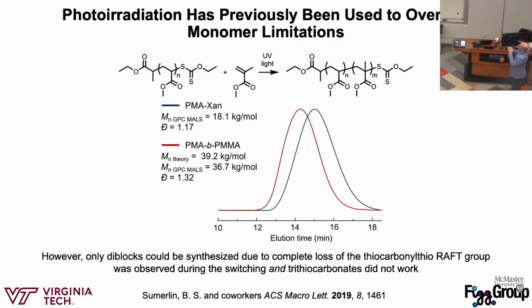But they were able to just homolytically cleave this through UV light, and then they can make this block copolymer of methyl acrylate and methyl methacrylate. They actually lose a lot of the chain end also, even though I have it drawn here, but you can chain extend it. The big issues with this is that you lose the chain end retention, and then this only works for xanthates. If you ever do RAFT polymerization, or you want to get interested in doing RAFT polymerization, xanthates are very rare in conventional RAFT polymerizations that you do because they don't lead to as good of control due to some of the energetics.